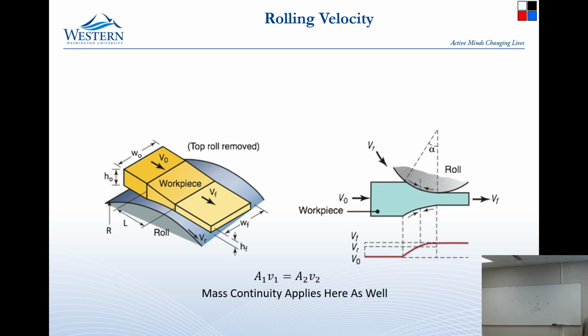and because it leaves at a different speed, if you think the roller is rolling at some velocity, the material's coming in at one velocity, it's leaving at a different velocity. Well, that means the material is accelerating through the rolling process. And what that means is that there is only one point along the roller where the roll and the material are going the same rate. Where you're on the thicker side, the roller is going faster, and when you're on the thin side, the material is going faster. So what this does to rolled materials is it burnishes a surface.